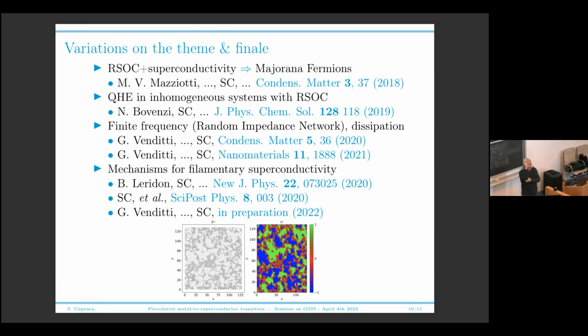So you have a situation. Imagine that in your system, because of disorder, you have domains, the blue and the green, where your charge density wave parameter, the Z component of the spin, points along Z in the positive direction, this is green, or along Z in the negative direction, this is blue. Now imagine that for some reason this is driven by disorder. We obtain this by disorder in the analog of the spin effective model.